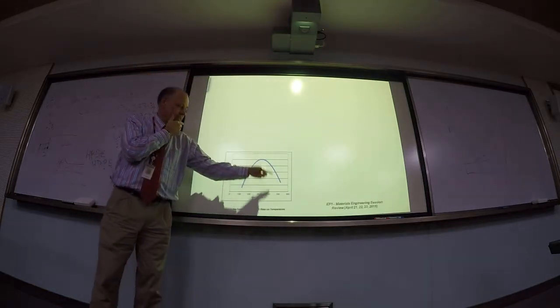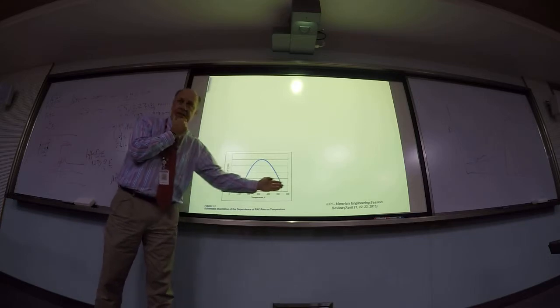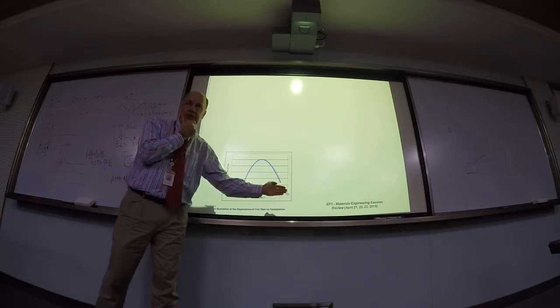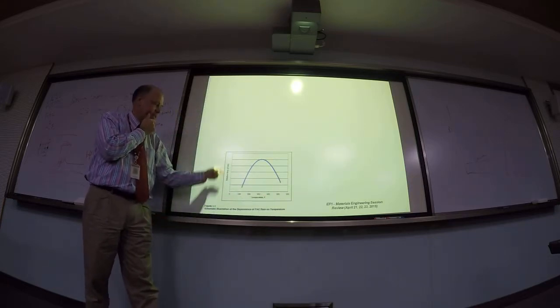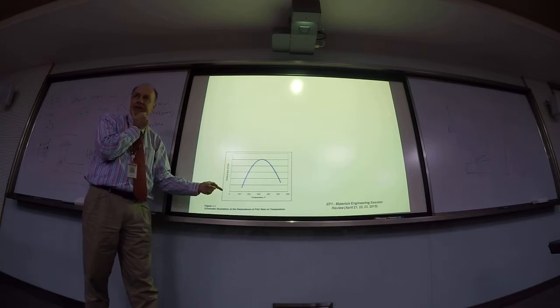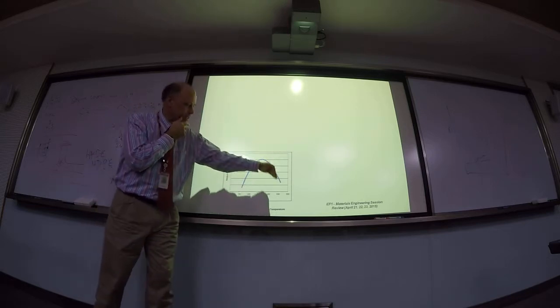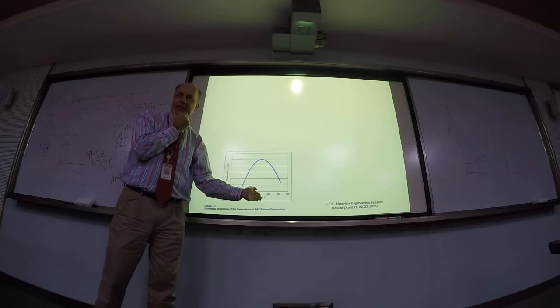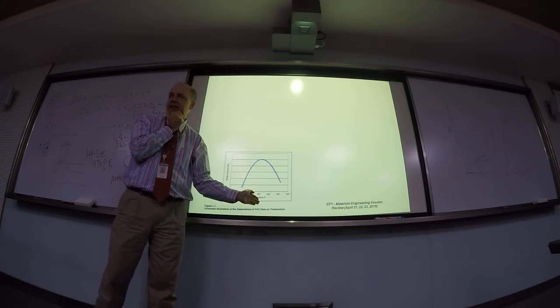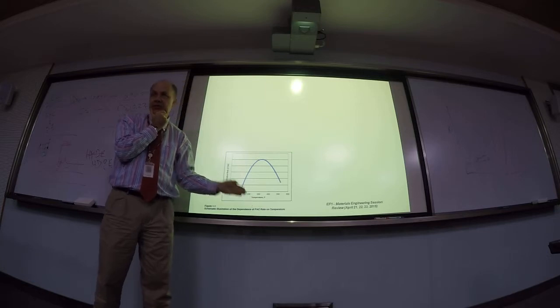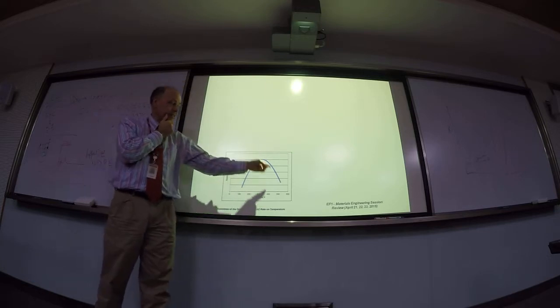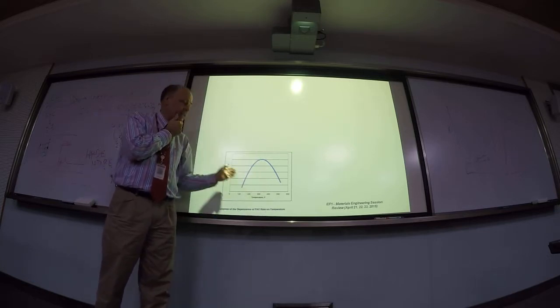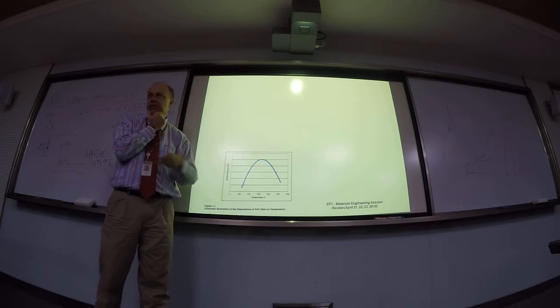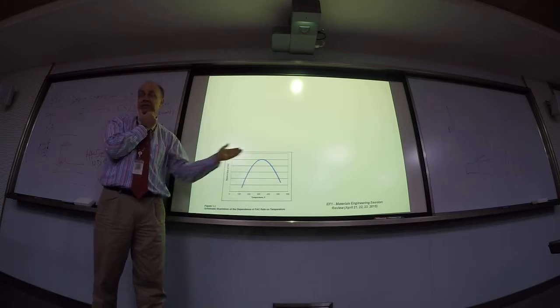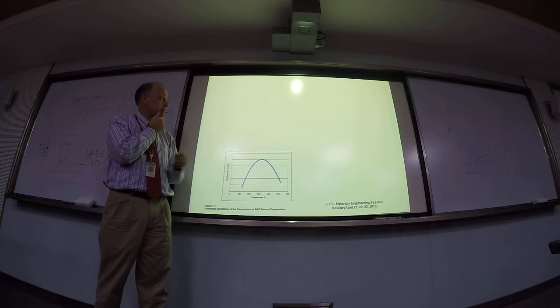What does this curve show us? What's this way? Temperature. This is FAC rate, right? So FAC has a worst condition. What temperature? 300 Fahrenheit, 150 centigrade, right? So there's a good chance you'll see a curve like this on the test, but it won't have any label on the axis. It'll say, what does this shape show? And you say it's FAC versus temperature, right?